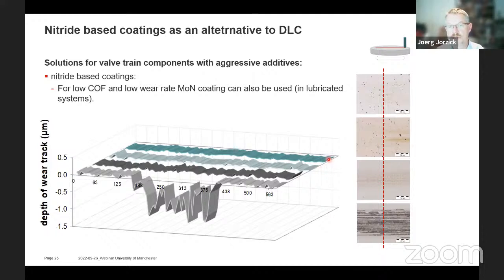Again, one with a standard lubricant and one with a lubricant with the high concentration of the MoDTC. And here, looking at the wear track, you see that this behavior is more comparable to what we see here with a DLC with a standard lubricant. So in case the additives are concerned, then the molybdenum nitride can be an alternative to the carbon-based coatings. And that is one of the reasons why it was used for this special piston pin application.